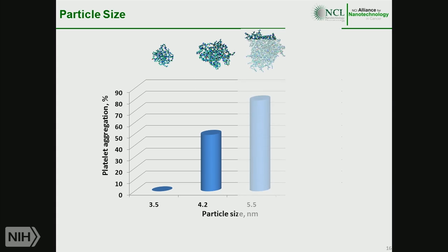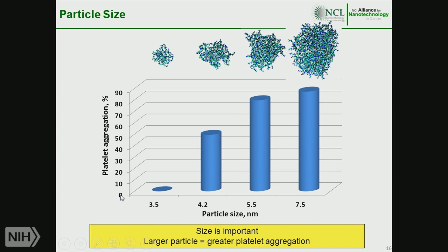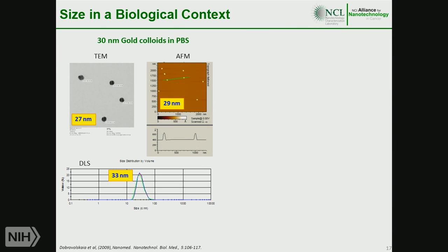You see in this case, an increase in size of PAMAM dendrimers results in an increase in the particle reactivity with membranes of platelets, which causes platelet activation and aggregation. So in this example, I show you that size is important. The larger the particle, the greater the platelet aggregation. But it is important to recognize that particle size under pristine conditions and in a biological environment are different things.